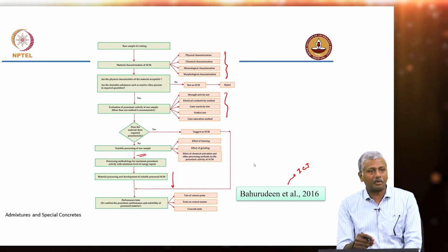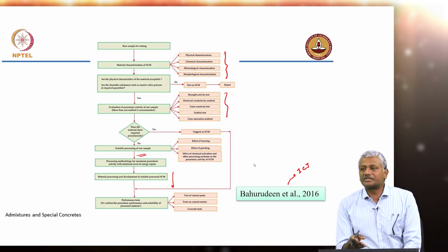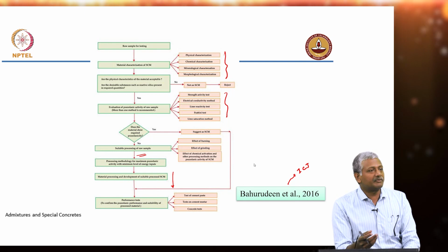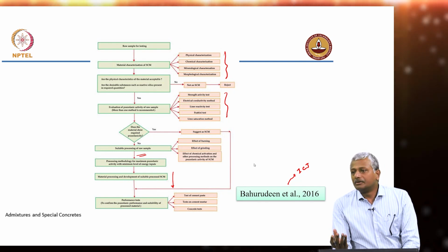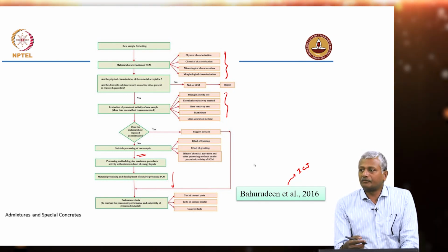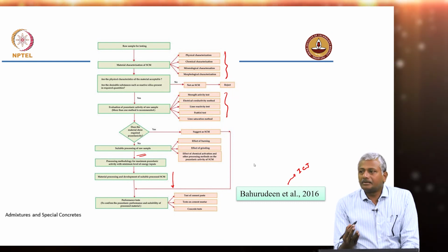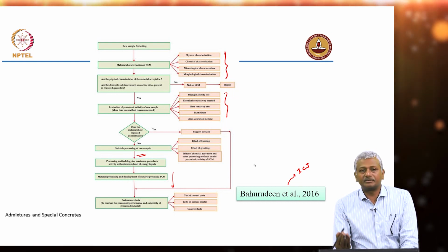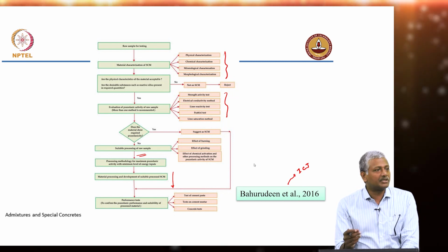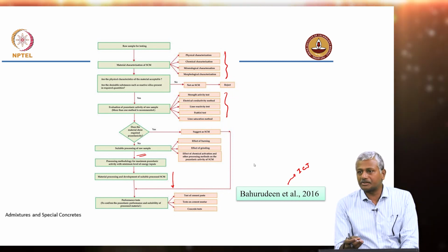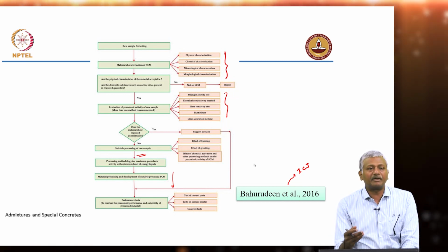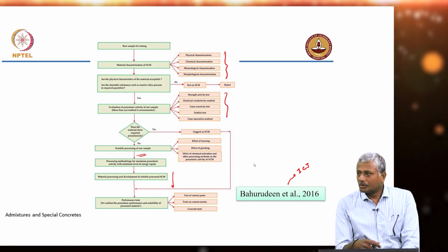Okay, I have not specifically devoted much of our later discussions when we talk about chemical admixtures to compatibility problems, but some of the aspects are quite clear. For instance, when you are replacing cement with a much finer material, you can expect that the superplasticizer demand will increase. Yeah, when you replace cement with something which is nicely shaped like fly ash, when you have spherical particles of fly ash, you can expect that the demand for superplasticizer is expected to go down.